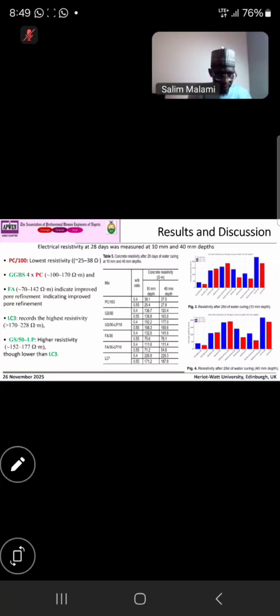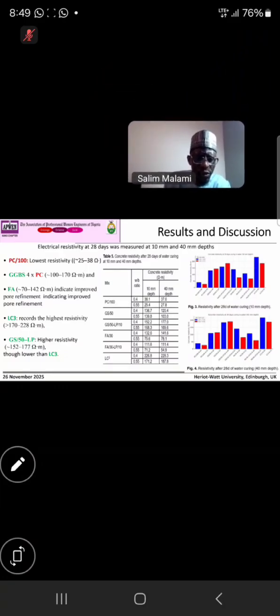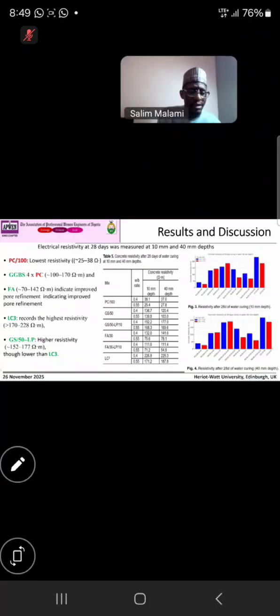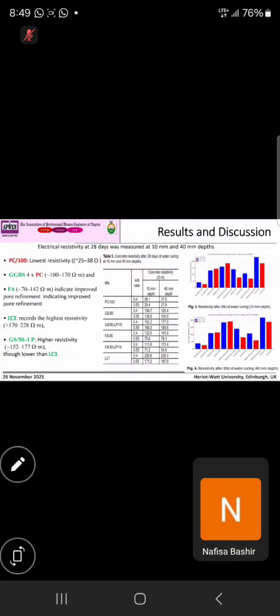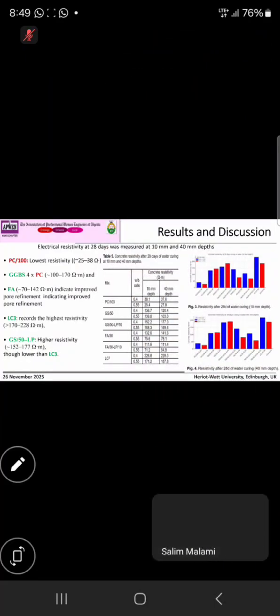We use LC3, the concrete with clay that is available all over. So this LC3 has higher resistivity compared with all, with around 170 to 228. Then GGBS with limestone powder also has higher resistivity, but it is less than that of LC3. This means LC3 is a good concrete with high electrical resistivity that cannot allow electrical current to pass through the concrete. So this is the table showing the results.